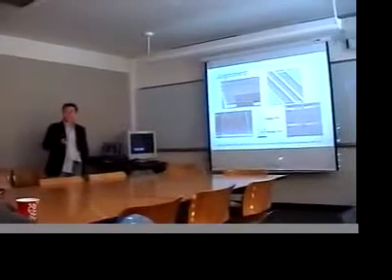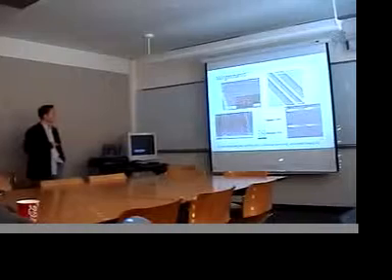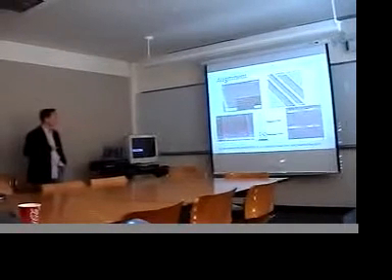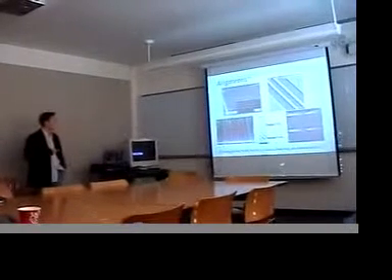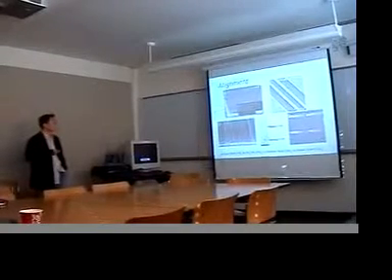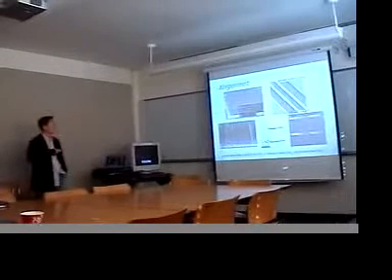So in order for us to make useful devices out of carbon nanotubes, you also need some alignment. So people explored using gas flow as a means. People have also explored PECVD. So you can see here that with the normal thermal CVD, it's kind of curly, but once they start using PECVD, it's much more directional. What they're actually using is an electric field that's caused by the sheath voltage. So this group directly used an electric field, and you can see here that the connections are very straight.